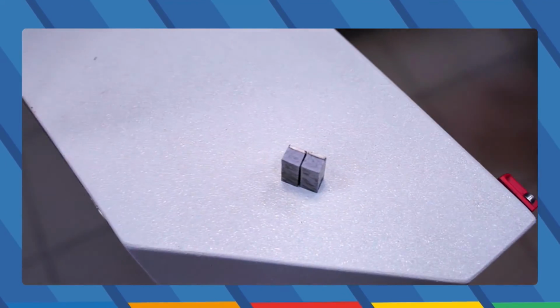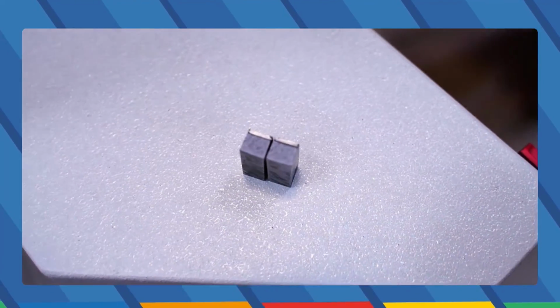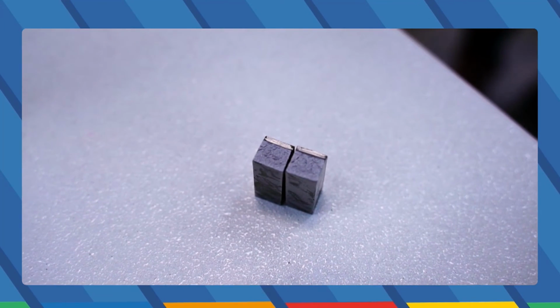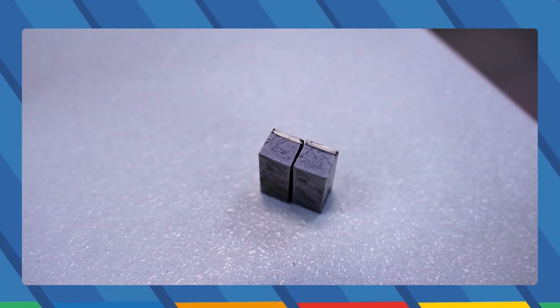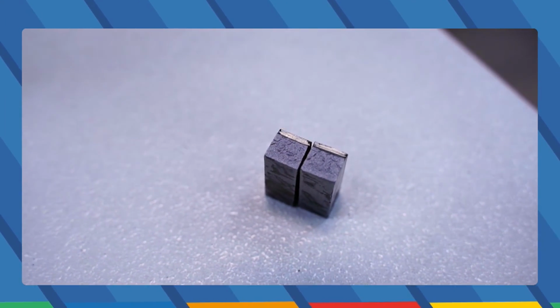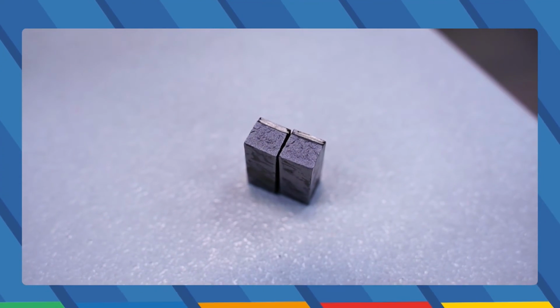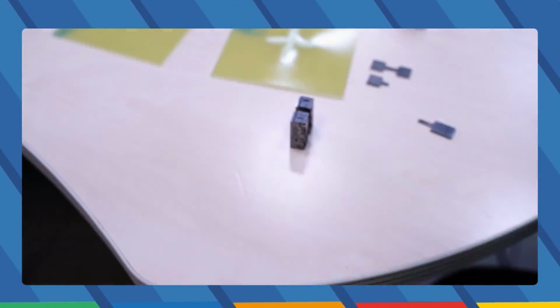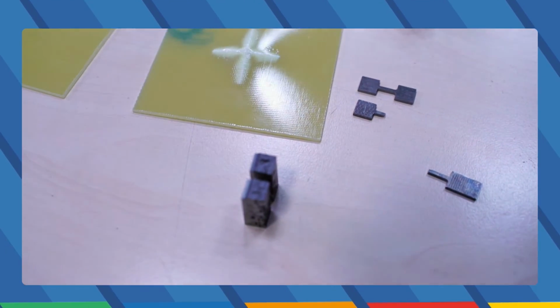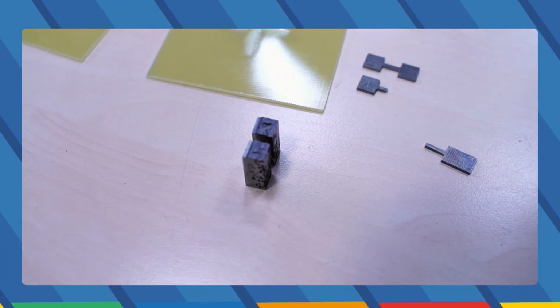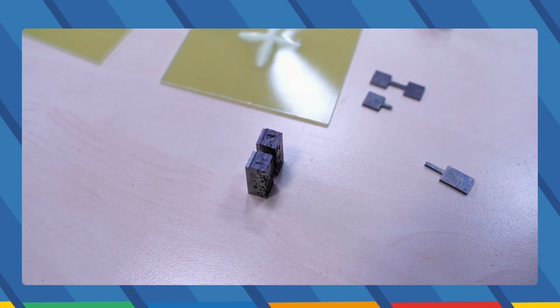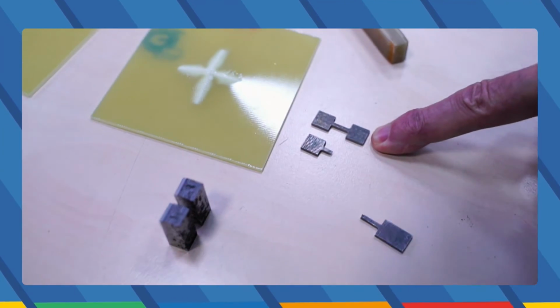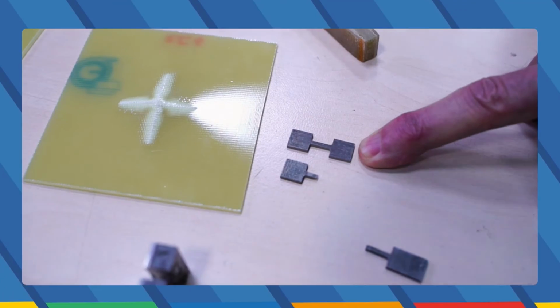You see the groove, and from this part the crack was going through the thickness of the sample, and the test is finished. You can see different objects for testing on this machine. This is the same test for fracture toughness, and here a small sample for the dynamic tension.